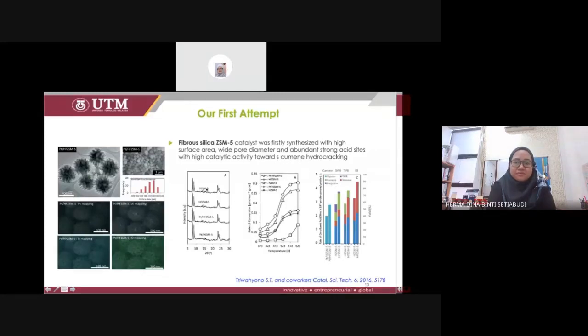This is the XRD result. As you can see here, they are similar, just different in intensity. This is the Pt ZSM5, the commercial one loaded with Pt. This is the Pt on fibrous. This is the bare commercial, and this is the bare fibrous ZSM5. So we can see almost similar, so we can say that our attempt is successful.